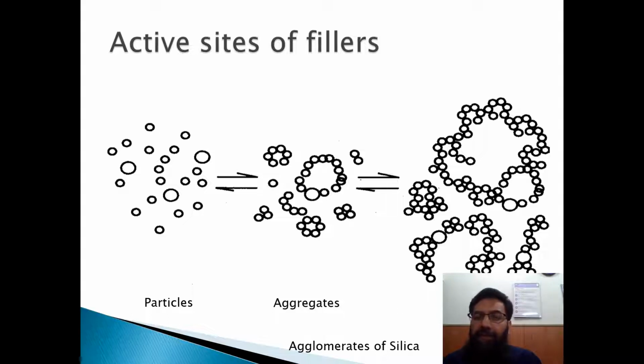can't get better reinforcement because most of the sites are filled with the hydroxyl group, and the presence of those hydroxyl groups makes the silica inactive. So silica would not give you better reinforcing property, and that is the main factor due to which silica could not be used as reinforcement for a longer period of time. But nowadays we do have some treatment mechanisms available. We have different types of silanes, which can interact with the hydroxyl group and make it non-polar, or make it more interacting with the polymer chain.